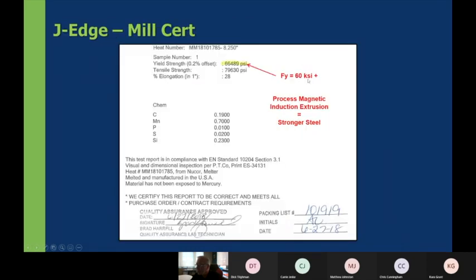Here's a mill cert where we show that it's above 60 KSI, so we're getting that stronger strength. One of the things that is very interesting about this is that it's a new process. It's relatively new in the industry, and it's a process of magnetic induction extrusion, and that equals a stronger steel. There's only a few places in the United States that's capable of extruding this type of steel product. Most of the steel that you see that's on a job site are typically rolled type of steel shapes.